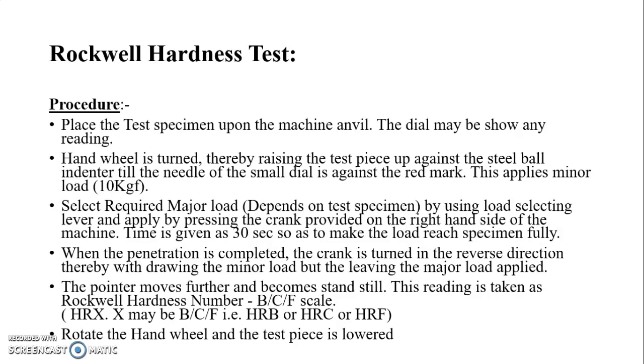Place the test specimen upon the machine anvil. The dial may show any reading. The handwheel is turned, thereby raising the test piece up against the steel ball indenter till the needle of the small dial is against the red mark. This applies the minor load, that is 10 kgf. Select the required major load depending on the test specimen by using the load selecting lever and apply it by pressing the crank provided on the right hand side of the machine.